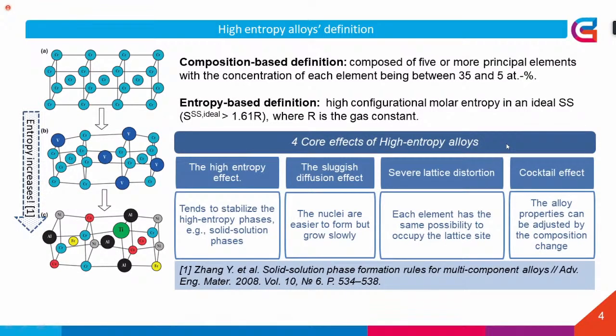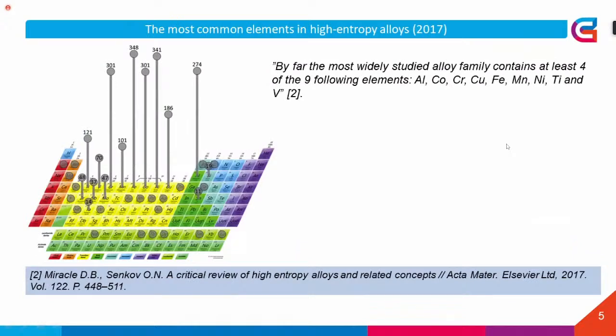The report is devoted to high entropy alloys production. These are alloys that have 5 or more elements with 5 to 35% content. They have high entropy, and the 4 key effects of high entropy alloys are shown. This is the high entropy, then the nuclei that are growing slowly, severe lattice distortion, as well as the cocktail effect.